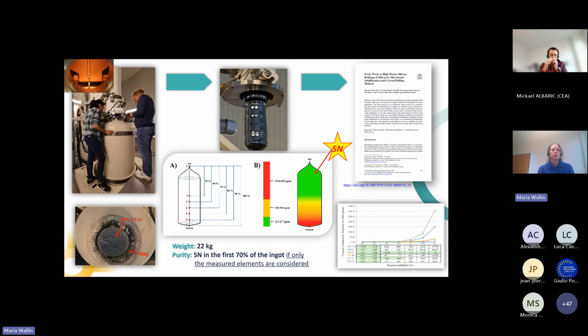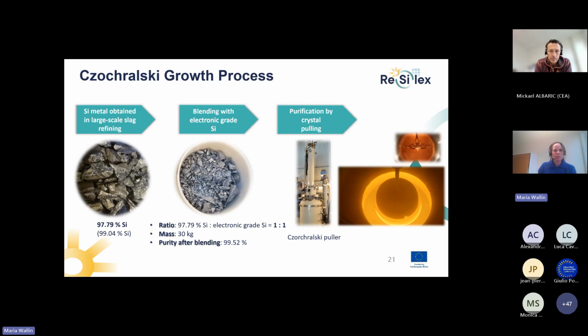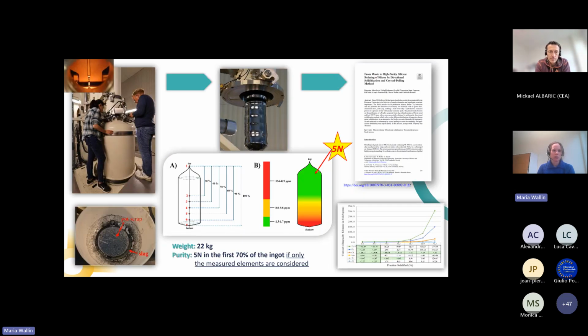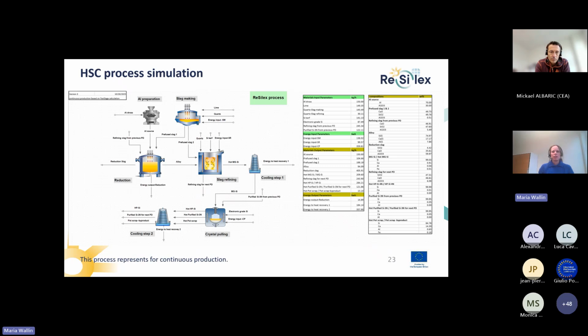And the final purity, what we were able to reach from this starting percentage of 99.52, was 5N at the top. So the first 70% of the ingot had a purity of 5N. And then you can see there in the crucible that we have some pot scrap and slag left. We have written a paper and presented this at this conference. And the main impurities that we see are mainly calcium and aluminum, which of course come back from the slag process in the beginning.